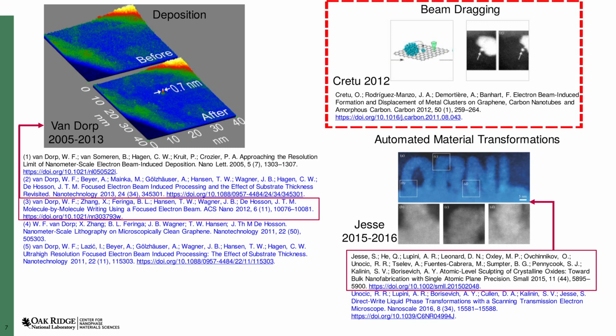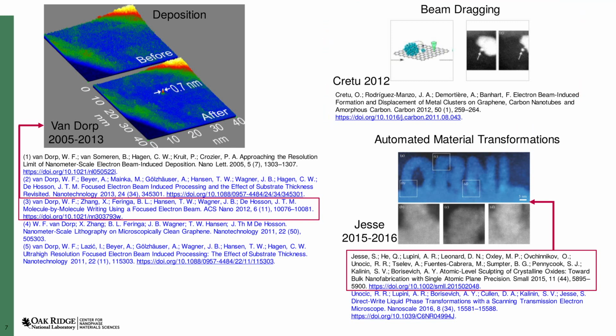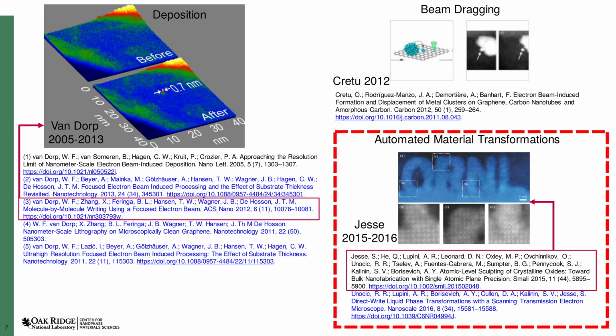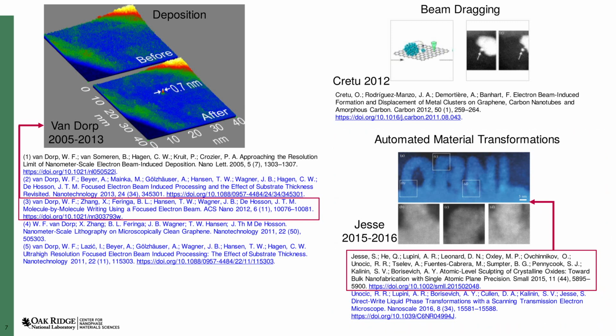In 2012, Cretu et al. showed that few-atom clusters could be separated from their parent nanoparticles and dragged a short distance across a graphene surface using carefully controlled e-beam irradiation. In 2015 and 2016, at Oak Ridge National Laboratory, we were also investigating beam-induced transformations. In this example, the letters O, R, and L were able to be crystallized one atomic plane at a time.